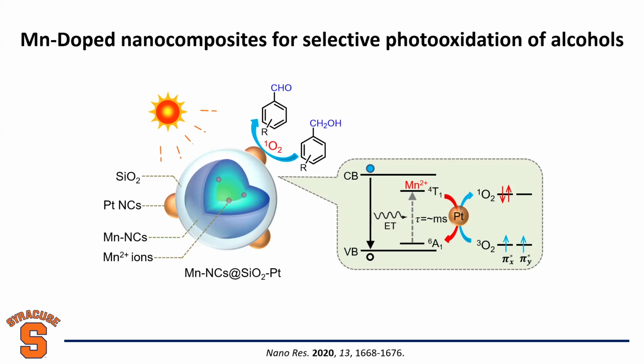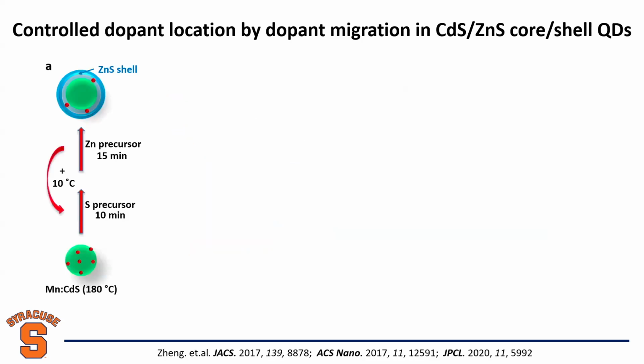Okay, yeah. So when we do this, we found an interesting phenomenon, because it's an energy transfer, right? From here to oxygen. Energy transfer is distance dependent. The longer the distance, the less efficient the transfer. The shorter the distance, the more efficient the transfer. So now we ask, can we manipulate the dopant locations inside the crystal, either on the surface, in the core, or at specific depths of a nanoparticle? So we want to go to another level of dopant manipulation. This is kind of very fun. You can see this is how we do research, right? We start with some fundamental question, we make nanoparticles, then we go to the application. Then based on the application, we further identify some key important fundamental questions again. Actually, we found we can control the dopant location by directional dopant migration.